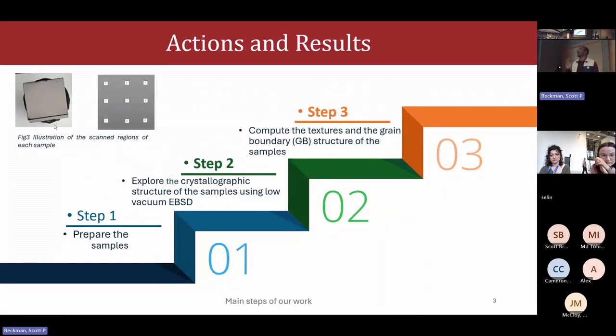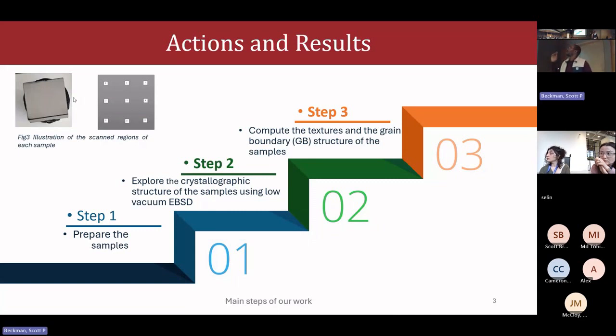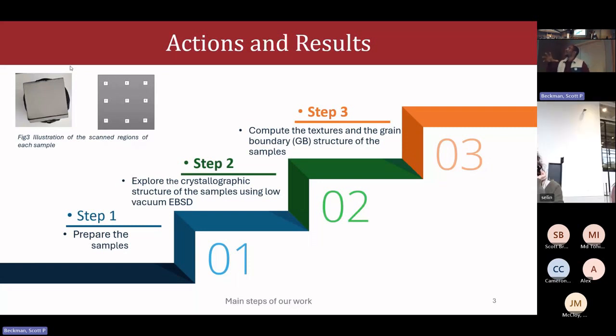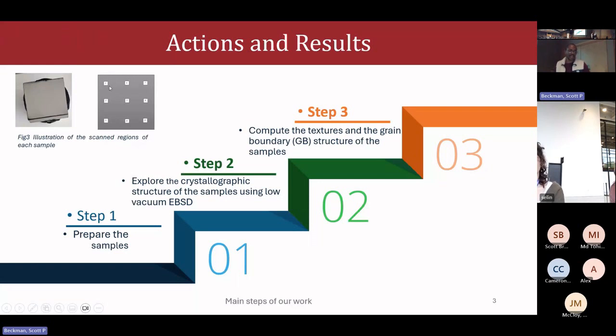It was really difficult to polish and we had a lot of noise when we were trying to get really big scans. So at the end we decided, instead of doing big scans, to do a lot of small scans at different areas to get something more accurate for statistics.